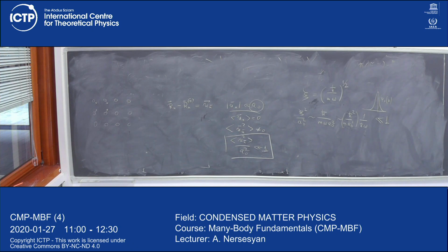There is no such a notion. No, there is such a notion as quantum crystal. There are some quantum crystals which are periodic, but whose number of lattice sites is greater than the number of atoms. It's a very interesting object. You understand, right? You may say if you take some atoms away and put them in the pocket and throw them out, then you also have some defects, some vacancies. No, there are no vacancies whatsoever.